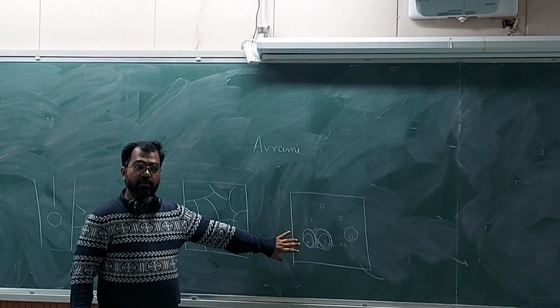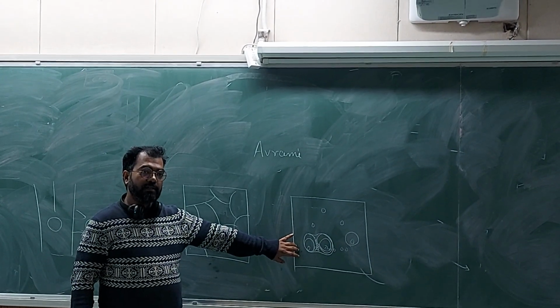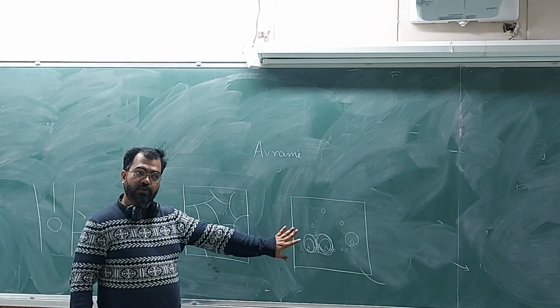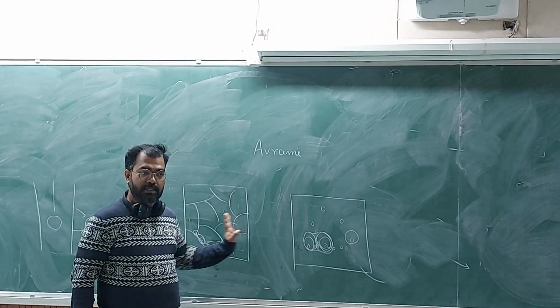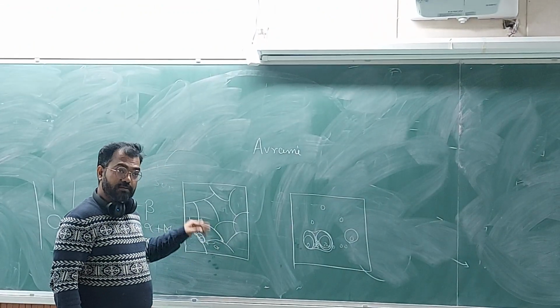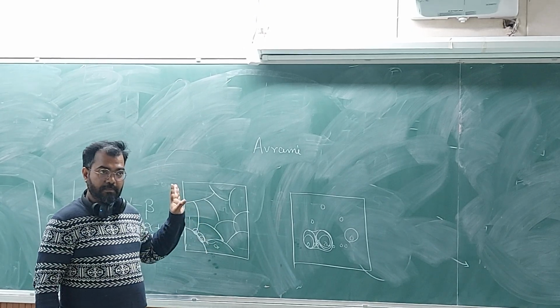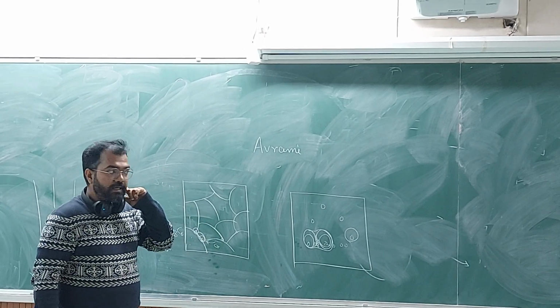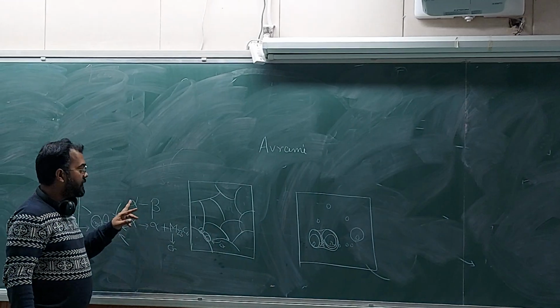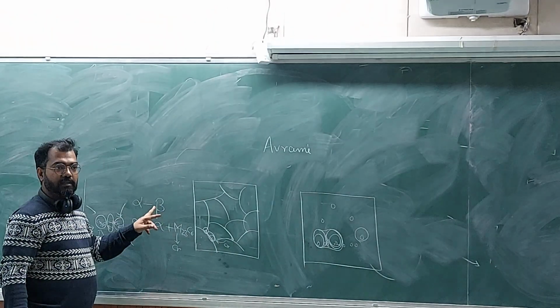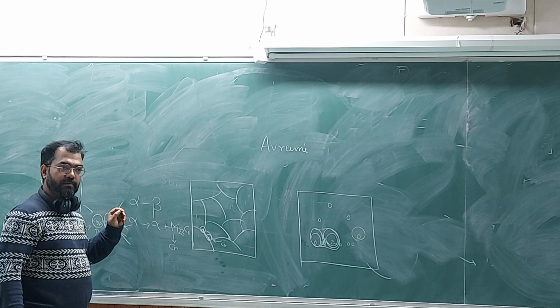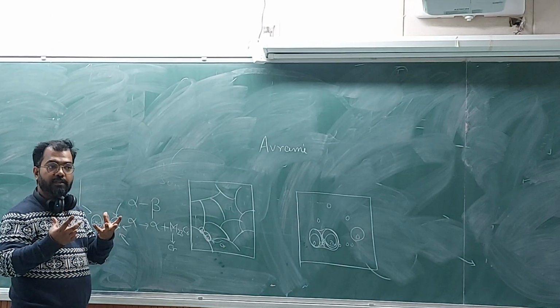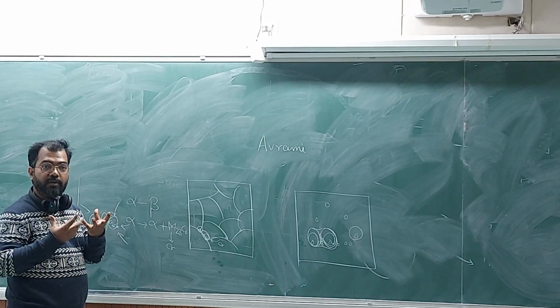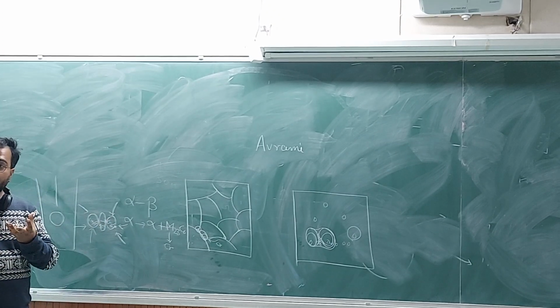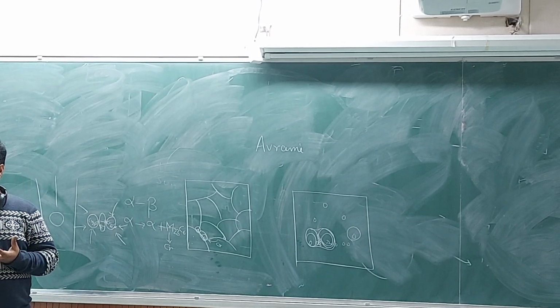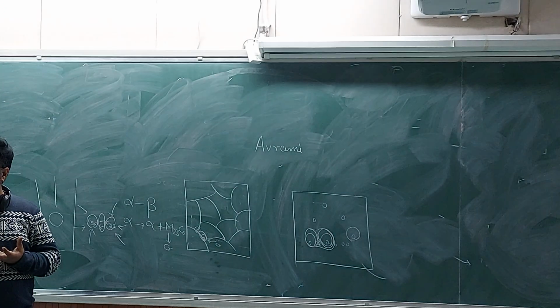Two voids grown together, the material will stretch and they will join together. So the coalescence part is missing in Avrami's case, in the case of precipitation. Even when you have complete alpha to beta transformation, then what will happen? Then the two grown areas will join together, but they will not coalesce because they will have a boundary between them. And that will be the new grain boundary.